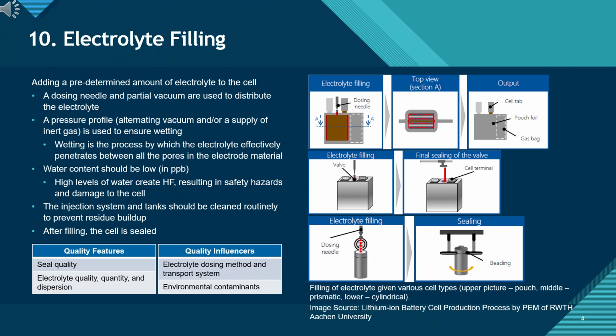Wetting is critical. The electrolyte must penetrate the porous electrode coating uniformly to enable efficient ion transport. Maintaining extremely low moisture levels, ideally in the ppb range, is essential. Any residual water reacts with the lithium salt to form HF, which can damage the electrodes, lower performance, and pose safety risks. Because of this, the injection lines and storage tanks must be cleaned routinely to prevent residue buildup and contamination. After dosing and wetting, each cell is sealed to prevent exposure to ambient moisture.